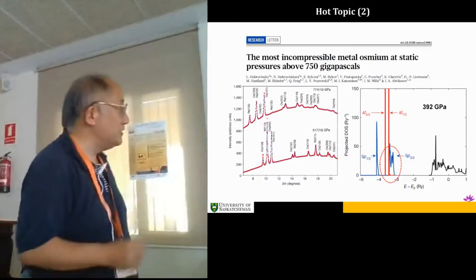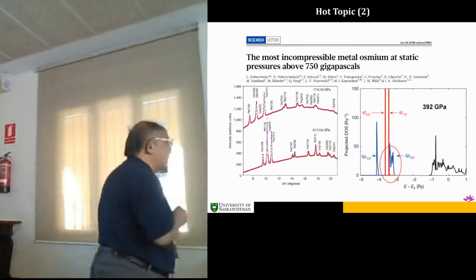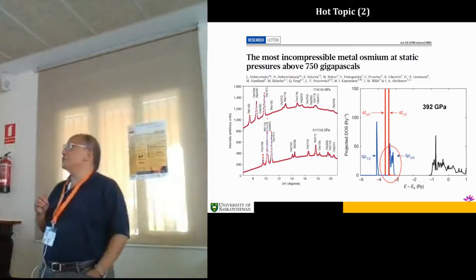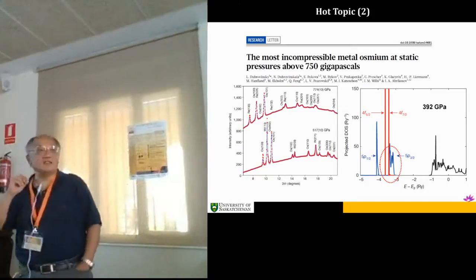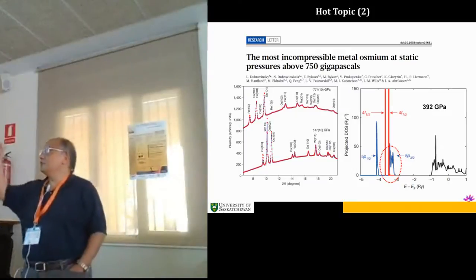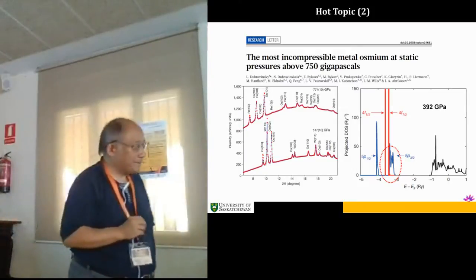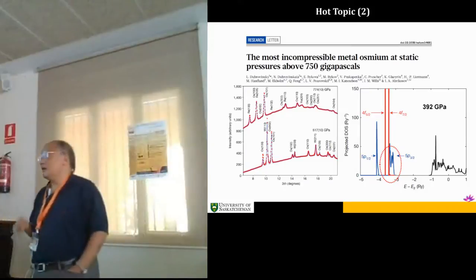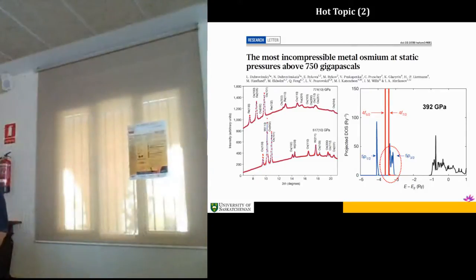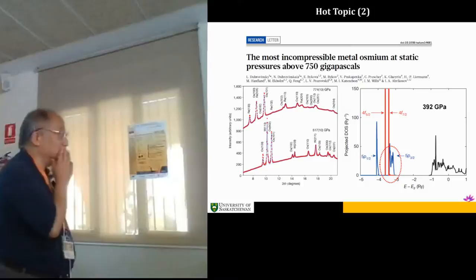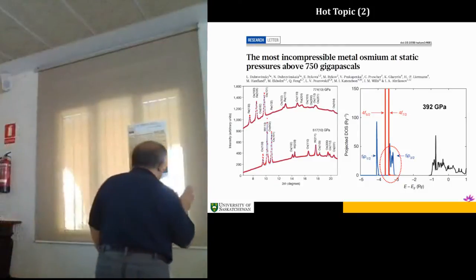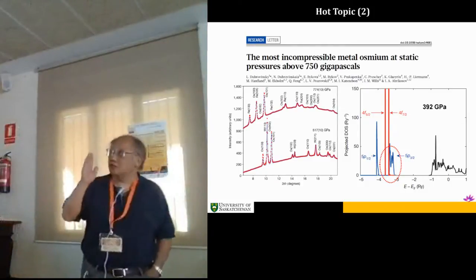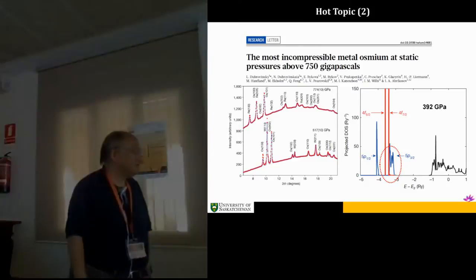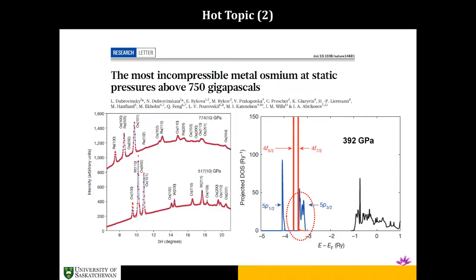So this came out even more recently, 3 days ago when I was preparing the talk. I did a search. And Dubrovinsky in Bayreuth achieved a pressure of 750 GPa. That's the highest pressure achieved. What impressed me is look at these two diffraction patterns. Okay, if you have done high pressure diffraction, I would just drop. Look at the resolution. Look at the line width. Some people at 20 GPa already have the peaks missing, okay?